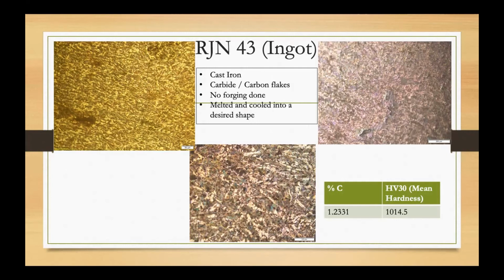You do not have crucibles. You do not have cinders. You do not have tuyeres from the site of Rakhigarhi. So the smelting must have been done at a place somewhere else. And the melted iron in the form of an ingot was brought back to the site. And again, the procedure of heating up and then manufacturing an artifact from the original ingot was done.